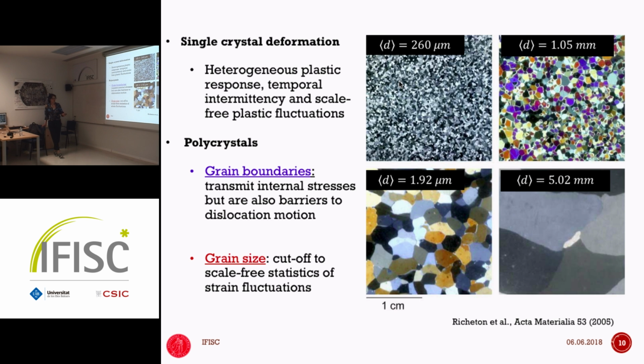And of course, if you go to higher scale, then you start to worry about the grain boundary in polycrystalline materials. And there's two new pieces of physics that come into the game. One is the effect of the grain boundary that acts like a barrier to dislocation motion. So they can't go too fast, because then they get absorbed at the boundary, they interact with the boundary. And then there's also a finite size effect when it comes to the statistics. And that introduces a new level of complexity.